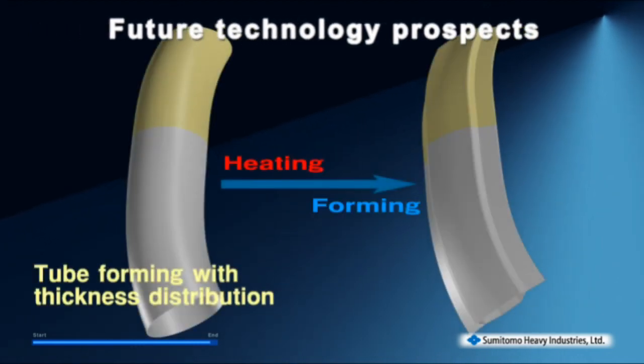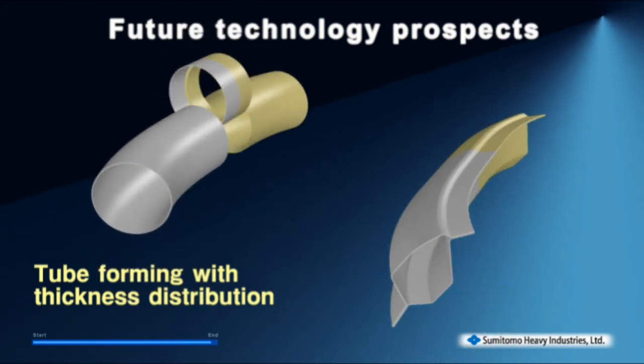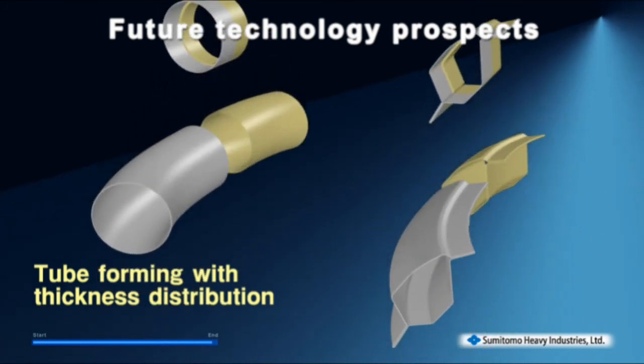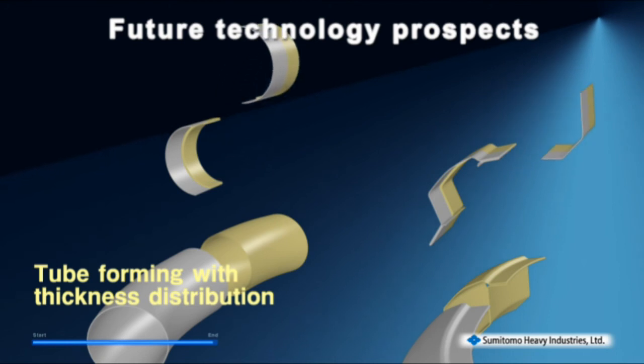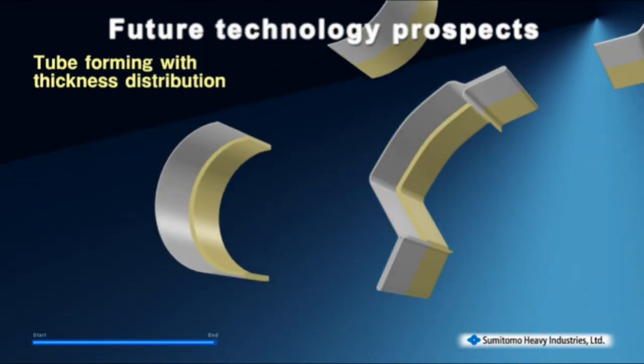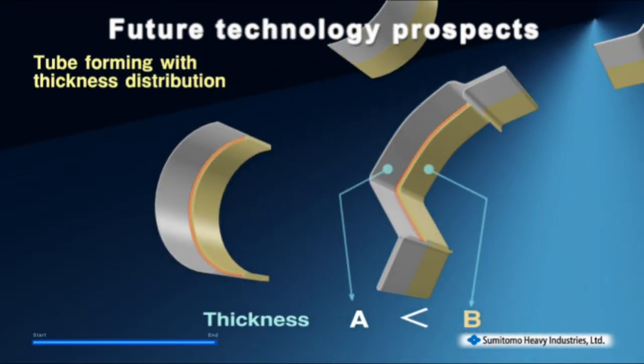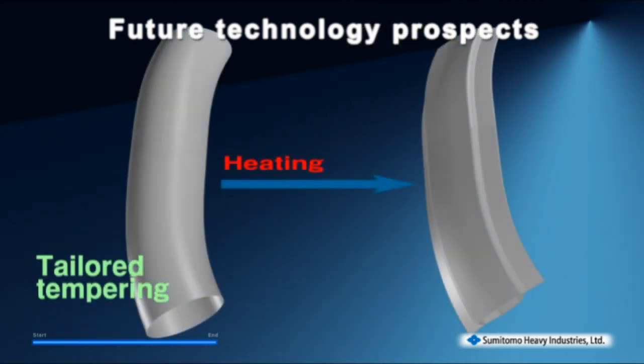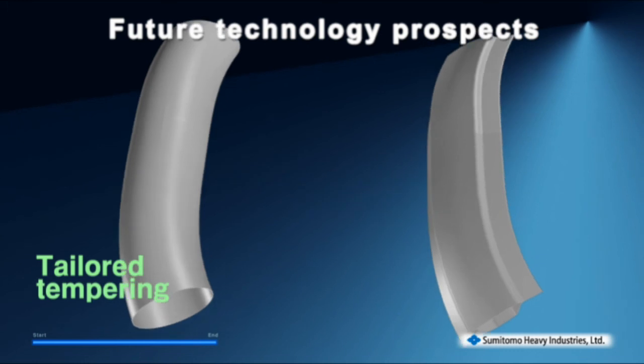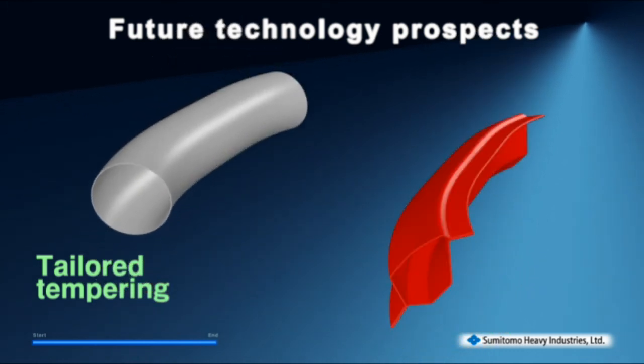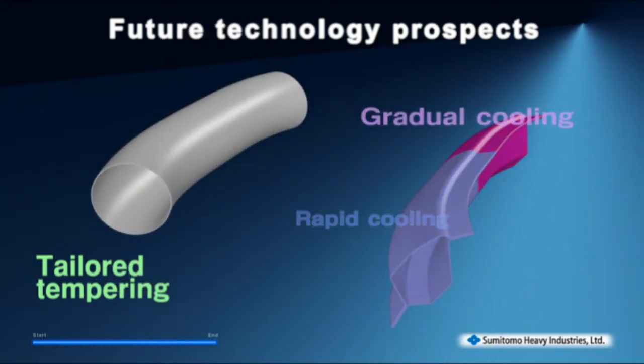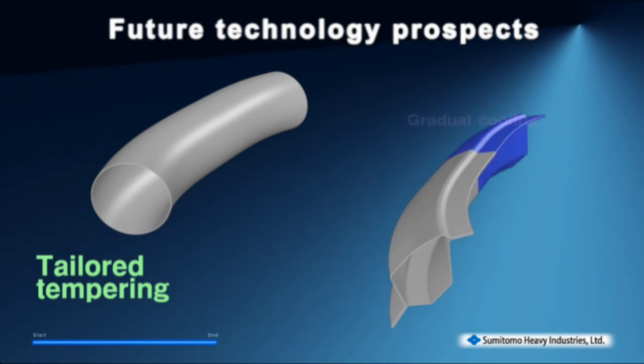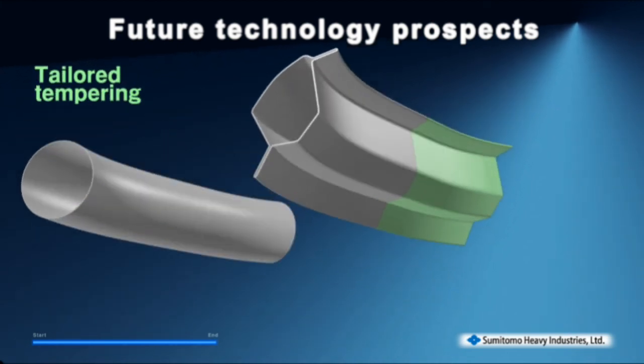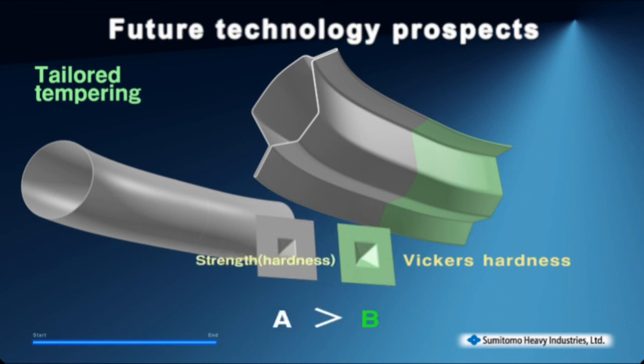One we're working on is developing a variable thickness molding technique that uses pipes of various thickness as the material and, in one step, hot forms and changes the shape of the part along its length. Another application we're developing is a variable strength technique that, like differential quenching used in hot stamping, can regulate the cooling rate of each section to vary the hardness between 980 and 1,500 megapascals.